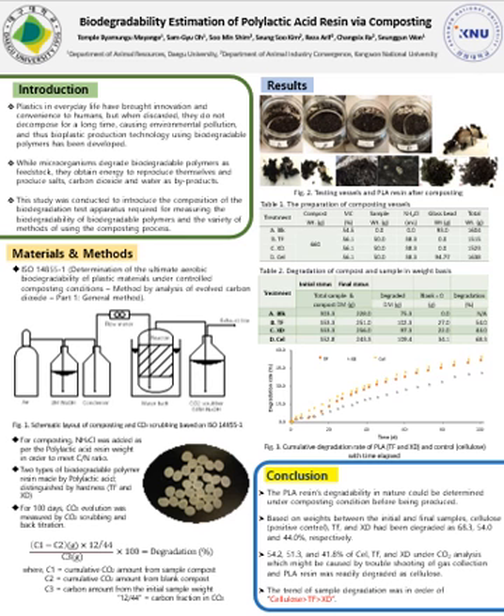Then for the composting, we add ammonium chloride per the polylactic acid resin weight in order to meet the carbon to nitrogen ratio, but we didn't add it in the blank compost. Then we also use two types of biodegradable polymer resin made of polylactic acid and distinguished by their hardness, which we call TF and XD.